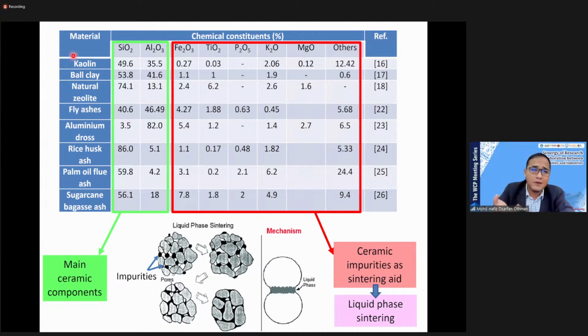We have a lot of kaolin, ball clay, but we don't have natural zeolite for now. But we have a lot of fly ash, aluminum dross, and so on. So for these types of material, the main composition is silica and alumina. The higher the amount of silica content inside the compound, the lower the sintering temperature to produce the membrane, because the sintering temperature for silica is much lower than alumina.